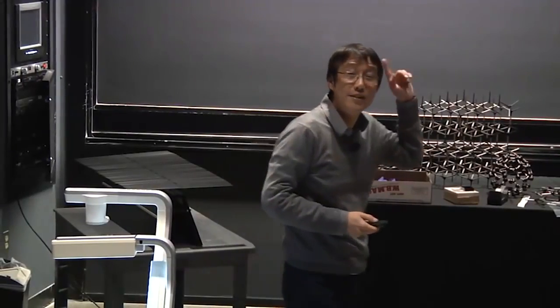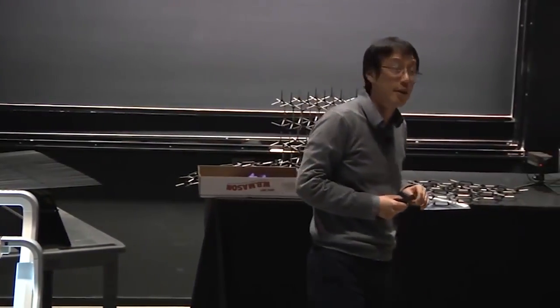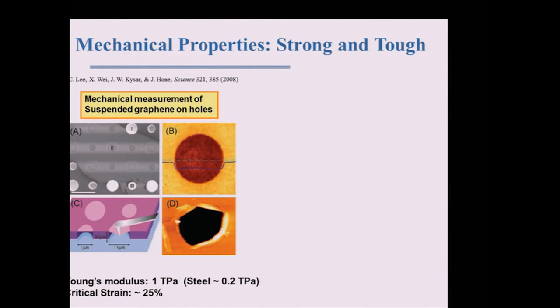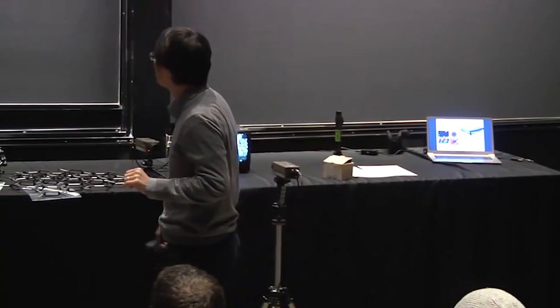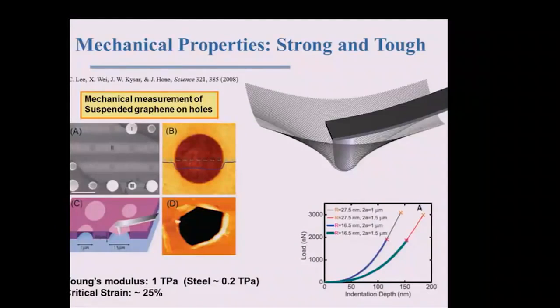More exciting is if you have the same sample, now this was done by my colleague at Columbia University, Jim Hone's group. What they did is, with this suspended graphene, they tried to poke a hole through using an AFM tip. And often they found that their AFM tip made of silicon is broken off. And only when they used a diamond tip, they could make the puncture through the graphene layer. And if you carefully measure how much force and how much deflection you induce onto this suspended graphene, they make the conclusion that this graphene can be extended up to 25% without any damage to the graphene sheet. And if you measure the strength, the so-called Young's modulus is extremely, extremely strong.